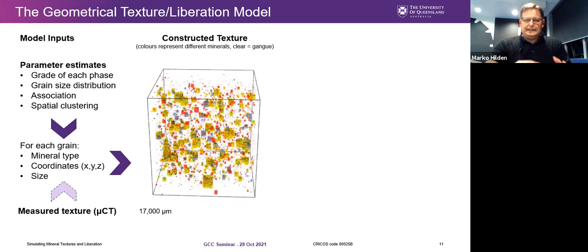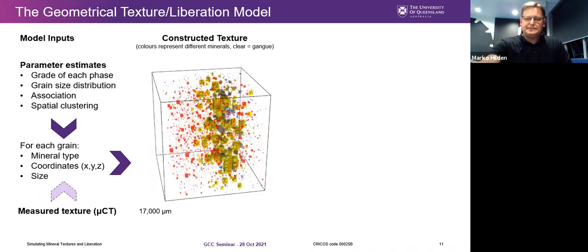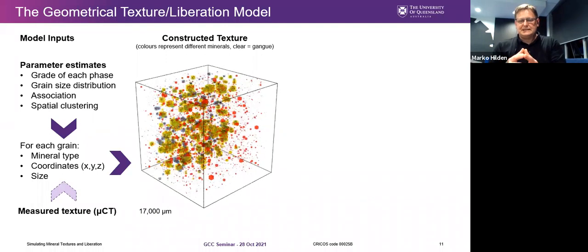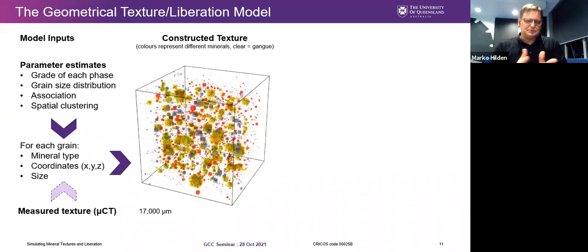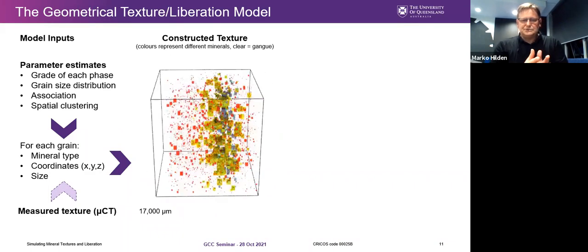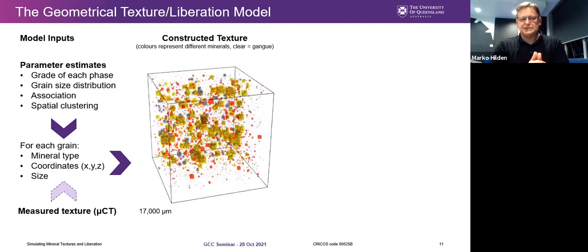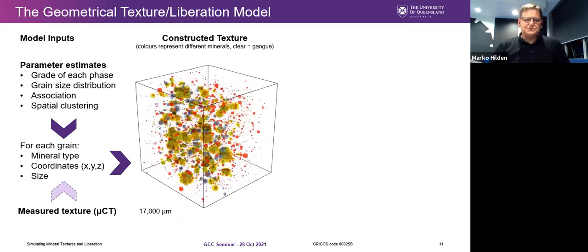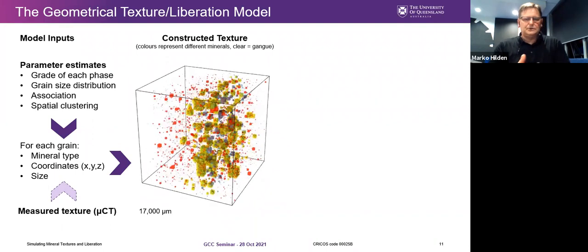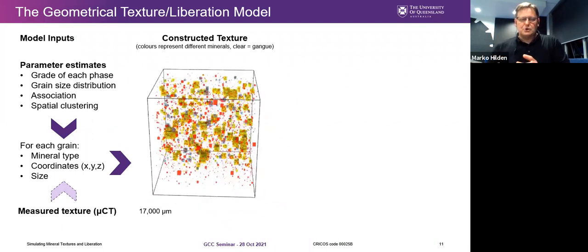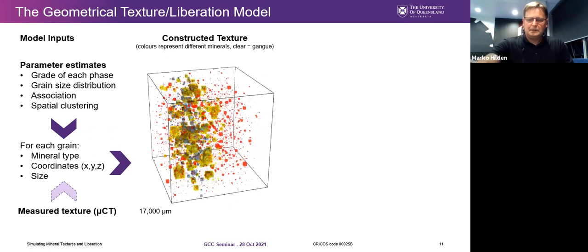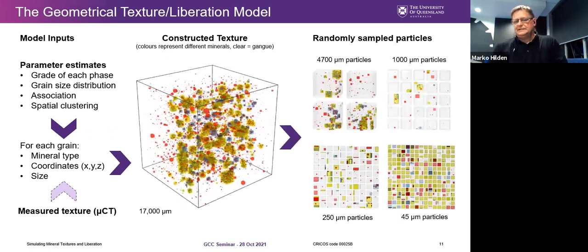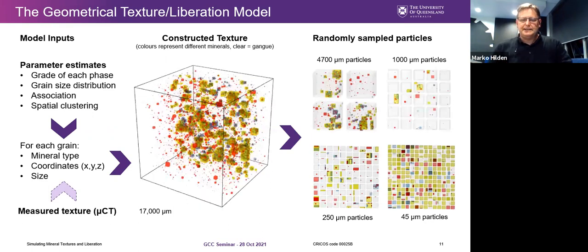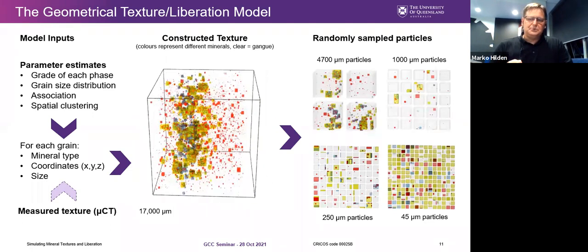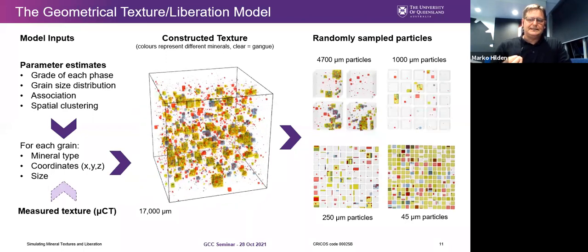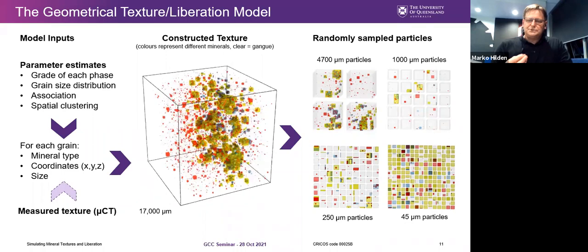In this example, I've just emphasized the spatial clustering. So some of the minerals are sort of clustered in this texture. And this property is important because you see this in real minerals where you have veining or parts of the rock being almost barren of mineral. And once we have this intact texture, we can then sample it to create virtual particles. So if we select a random point, we can calculate all the grains that intersect with a particle generated at that point.